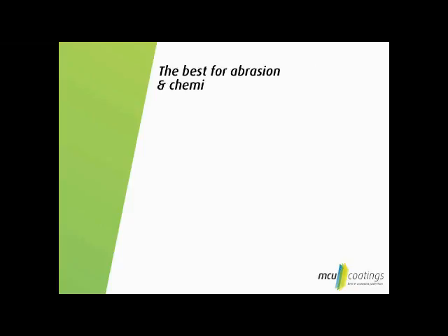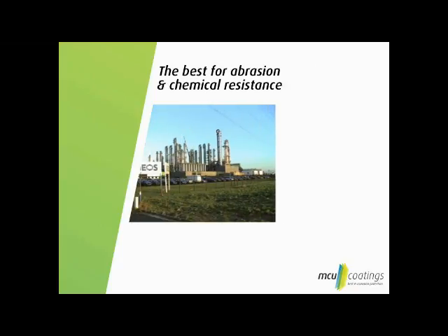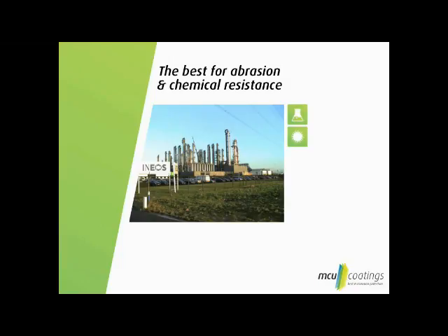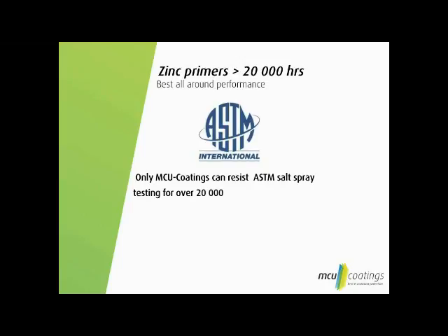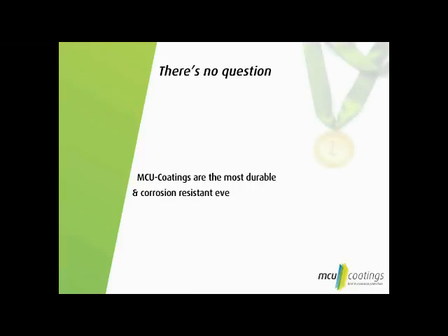In addition, MCU Coatings' aliphatic moisture cure top coats are the best of all urethanes for abrasion and chemical resistance, and like two-part aliphatic urethanes, have excellent UV resistance. The MCU Coatings' zinc primers offer the best all-around performance of all zinc-rich primers. Unlike their inorganic counterparts, MCU Coatings' zinc primers' unique properties allow their use on poorly prepared surfaces, a dramatic and significant innovation. Only MCU Coatings can resist ASTM salt spray testing for over 20,000 hours. After 3 years in the salt spray test, MCU Coatings still performed great, while the best conventional coating fails in only months. There is no question MCU coating systems are the most durable and corrosion resistant ever introduced.